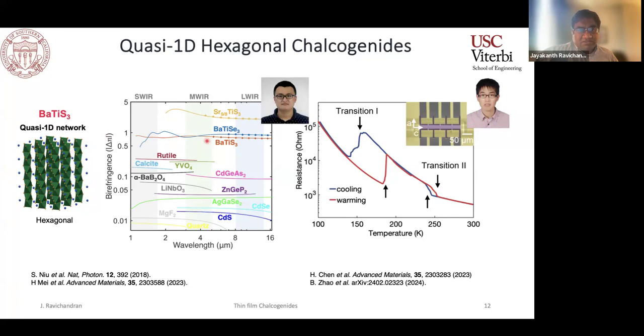One is that they tend to have extremely large optical anisotropy. What I mean by that is that the refractive indices, either the real or imaginary part, tend to be extremely different along the chain and across the chain. And this leads to large birefringence, large dichroic windows. Then you can think of using these materials for filters, or for wave plates and other polarizing optics that allow you to shape the wavefront of your light. And specifically, they seem to work extremely well in some part of the mid-IR, and also a large portion of your long-wave IR, which is of interest for the atmospheric window communication and sensing that I mentioned earlier.